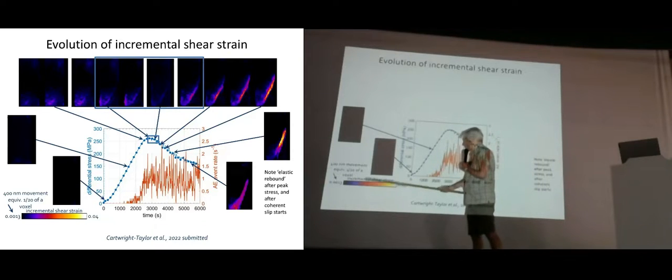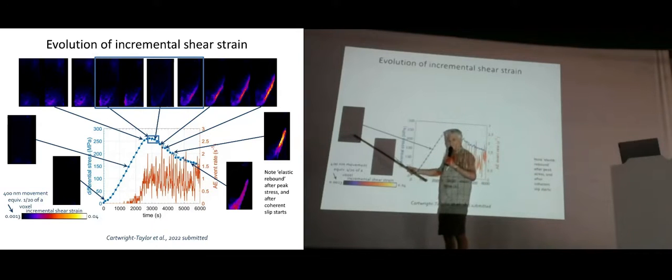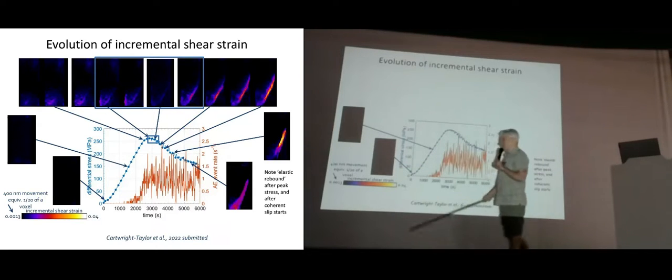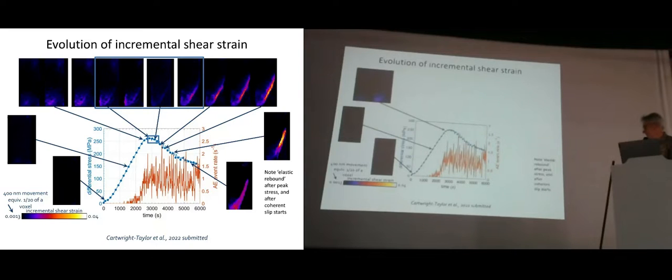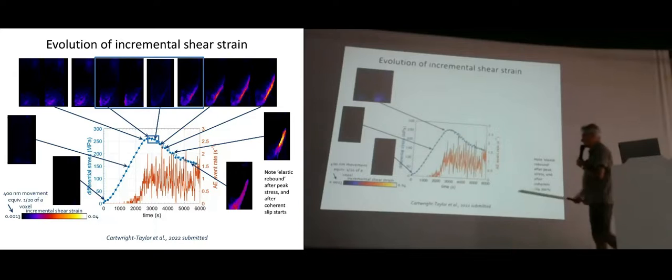And this is the shear strain. But can you see that? It's not very convincing, but it is there. Our interpretation of this linear phase is that it's predominantly elastic, but there is a compensated phase of damage and healing occurring all through this phase. So there's a dynamic balance of a small nonlinear component associated with compaction and maybe some incipient microcracking. And then that becomes more obvious once you get to yield, you start to see more obvious damage.